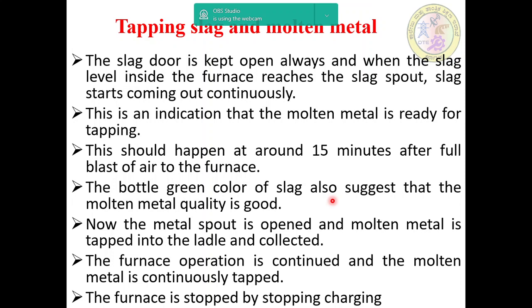And then next is tapping slag and molten metal. Here the slag door is kept open always, and when the slag level inside the furnace reaches the slag spout, slag starts coming out continuously. This is an indication that the molten metal is ready for tapping. This should happen at around 15 minutes after full blast of air to the furnace. The bottle green color of the slag also suggests that the molten metal quality is good.